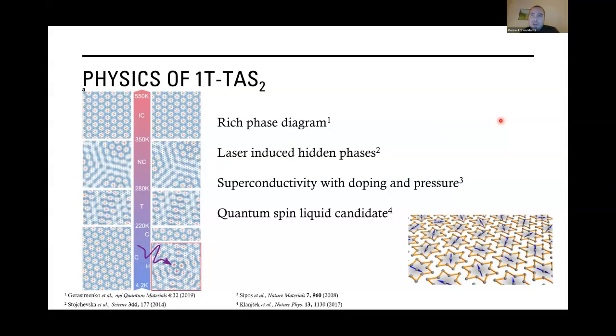So among the interesting phenomena of this material, there's a really rich phase diagram with many charge density wave states with different degrees of commensuration, from incommensurate to fully commensurate. Additionally, there has been a demonstration in the seminal paper by the group of Dragan Mihailovic of the existence of a hidden phase of this material. Upon doping and pressure, superconductivity appears. And what is interesting is that superconductivity only appears starting from phases that are discommensurate. And finally, since you have a Mott insulator, you can also have magnetic frustration. And this material has been proposed as a potential candidate for a quantum spin liquid.